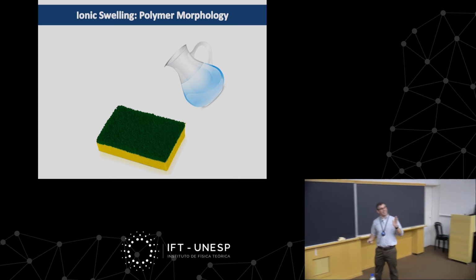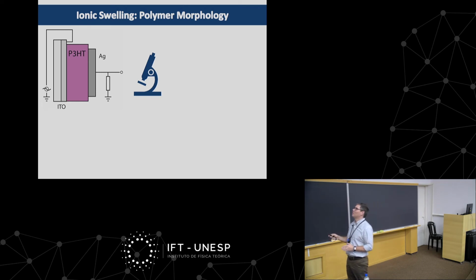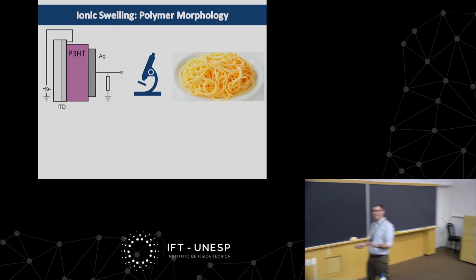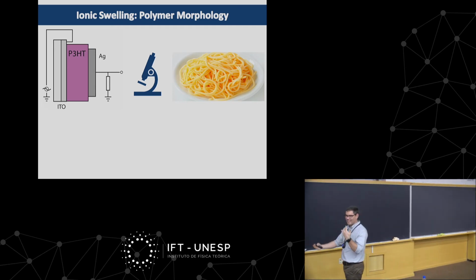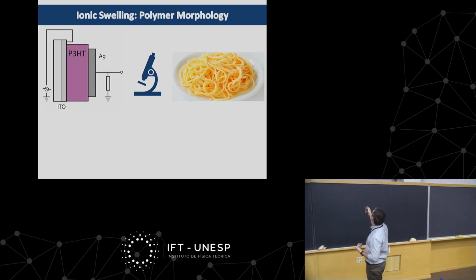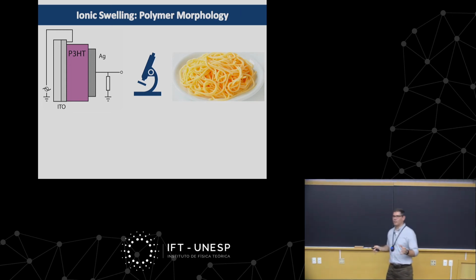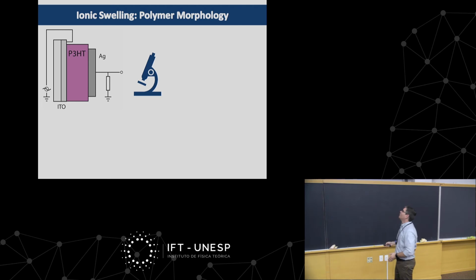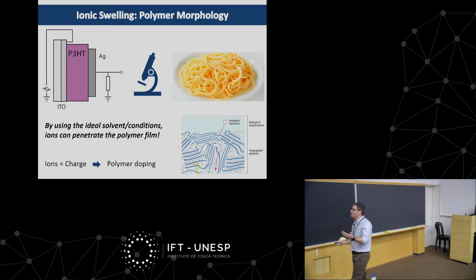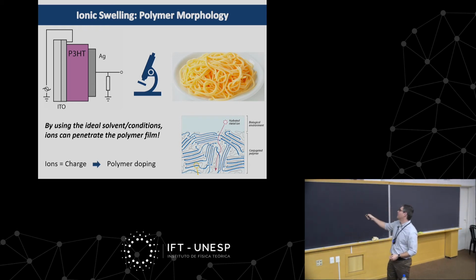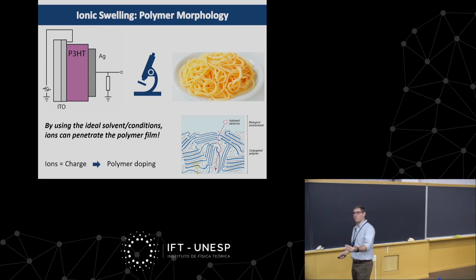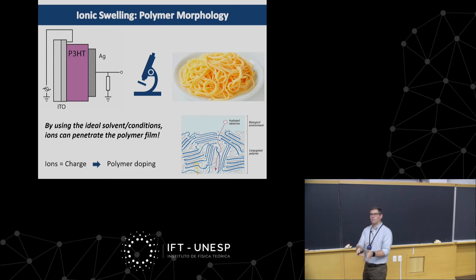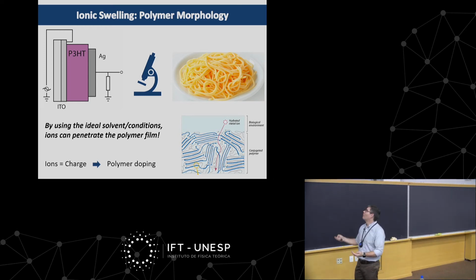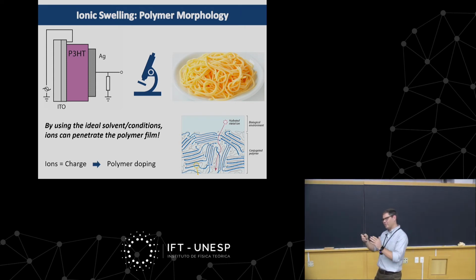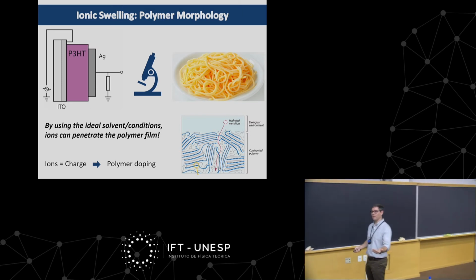And this exactly happens to your polymer. If you take that polymeric film and look at it under the microscope, what you see is basically a plate of spaghetti. Very long chains that are entangled one on top of the other, with a lot of different porous holes where, ideally, solvents and therefore ions could penetrate. In an ideal environment, ions and therefore solvents can penetrate in and start interacting with your polymer molecule. And when ions interact with your polymer, you create doping, because ions are charged atoms and charged atoms dope polymers. And therefore, by absorbing ions in that very intricate morphology, you can start doping your material.